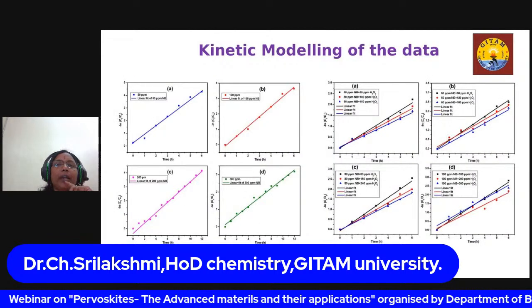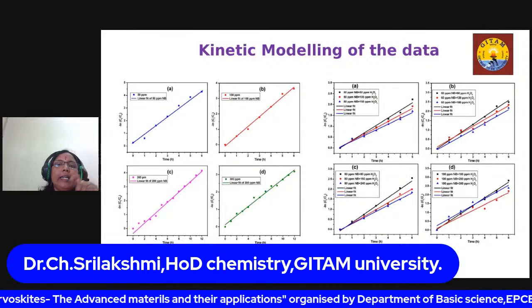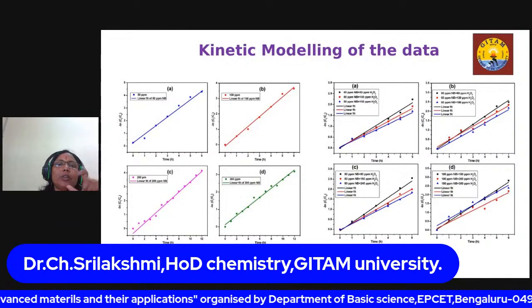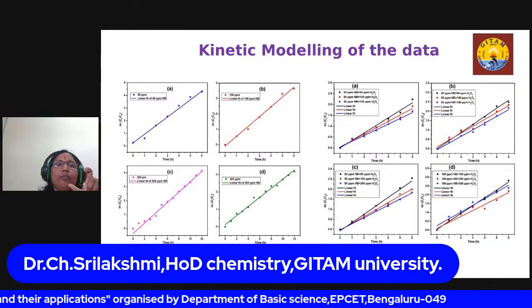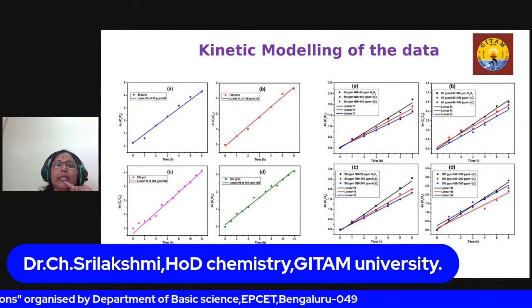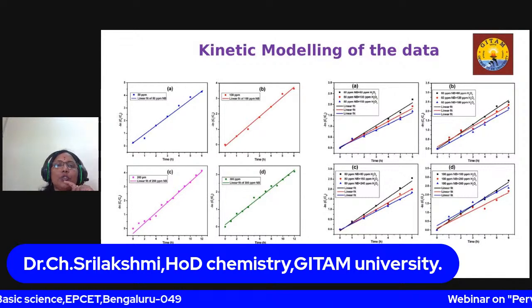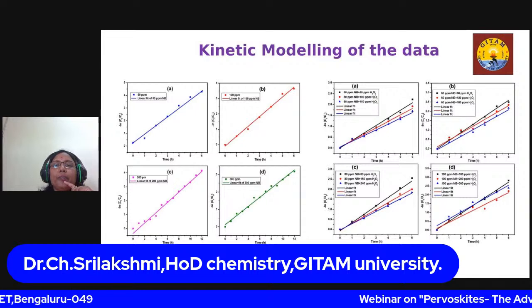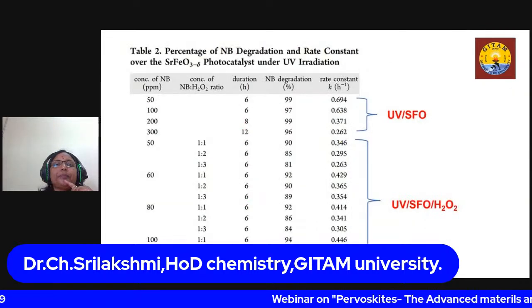We try to find out, and so we have modeled the data, and it fits nicely into the first order. It follows first order kinetics, and we have calculated the rate constants using the slope of these curves here, and we have plotted here. You can see